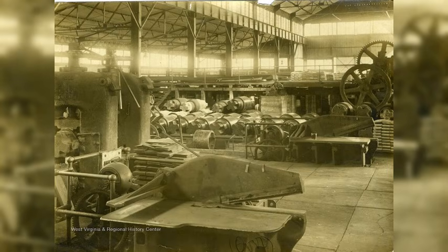The traditional hot-dip tin plating process was wasteful. Dipping steel sheets in molten tin resulted in thick, uneven coatings. A typical hot dip can used 1.5% tin by weight, with coating thickness varying from 0.0001 to 0.0005 inches, depending on the dipping time. Metallurgists had known since the early 1900s that tin could be electroplated onto steel, deposited atom by atom through electrolysis rather than wholesale dipping. Electrolytic tin plating could apply coatings as thin as 0.00005 inches, or 50 millionths of an inch, uniformly across the entire surface.